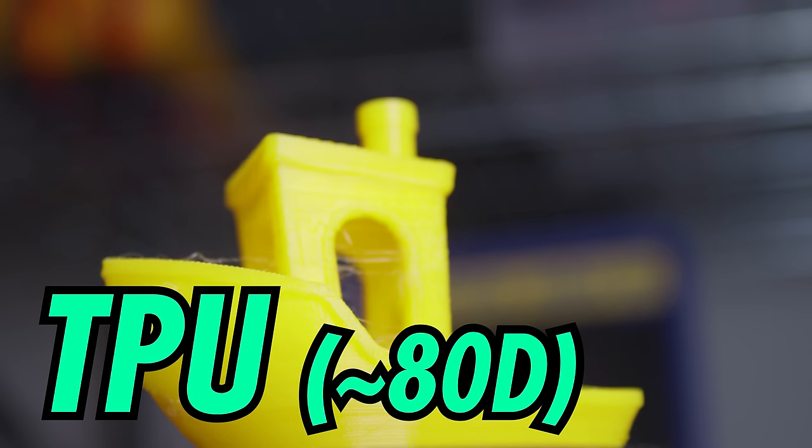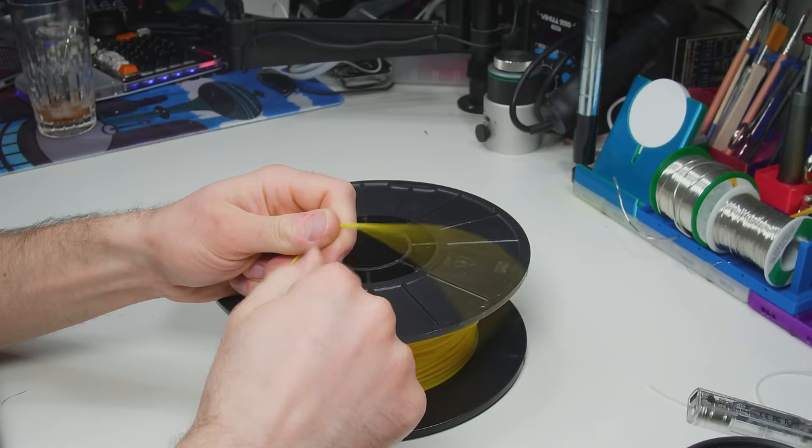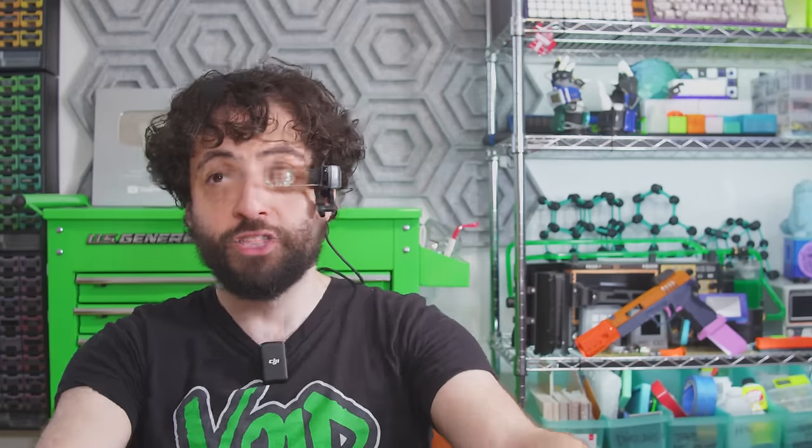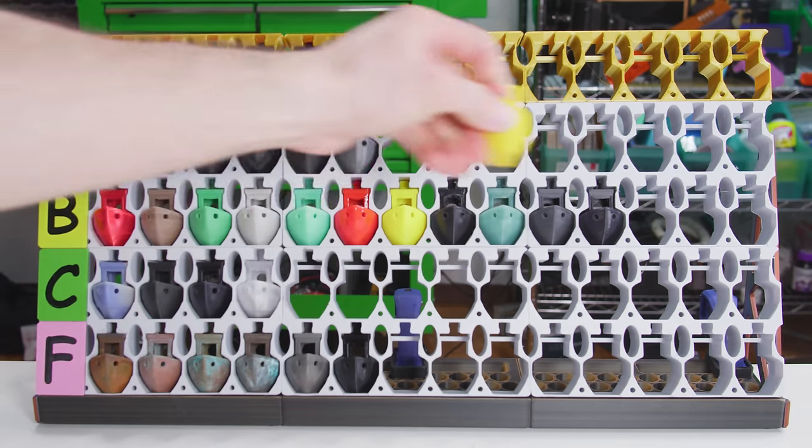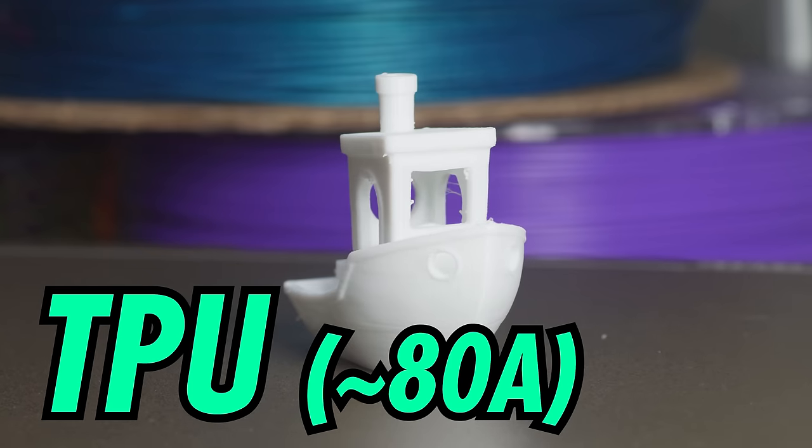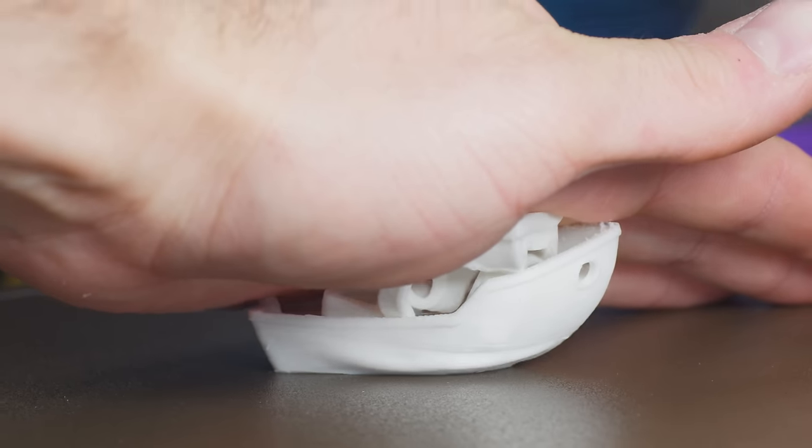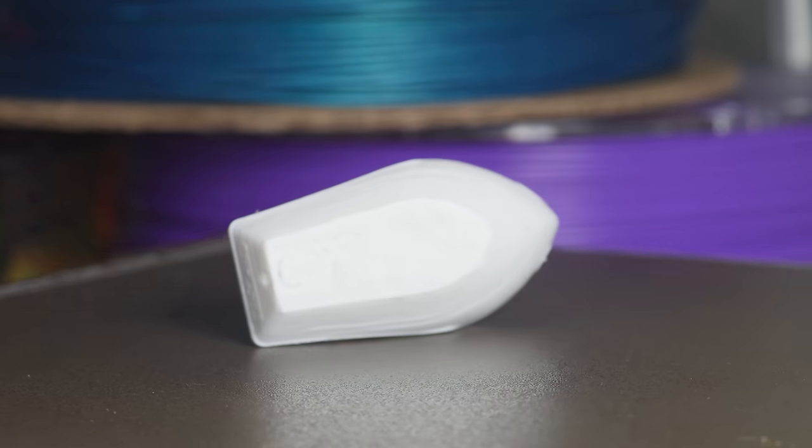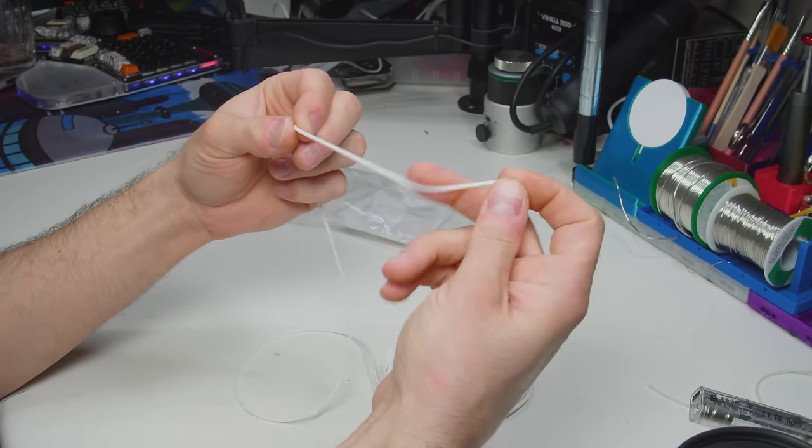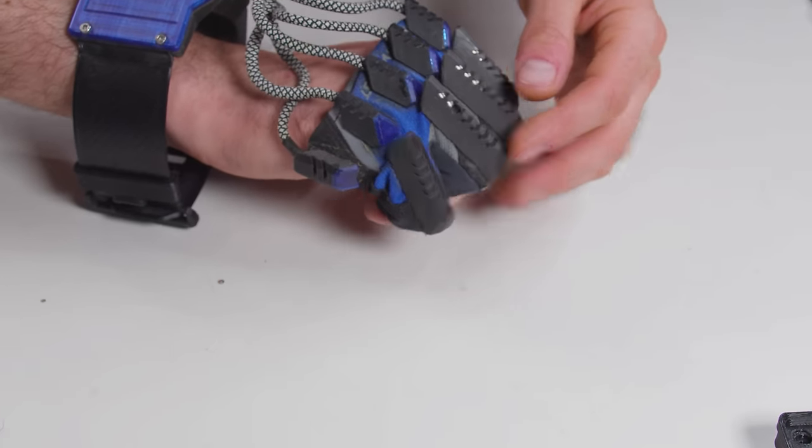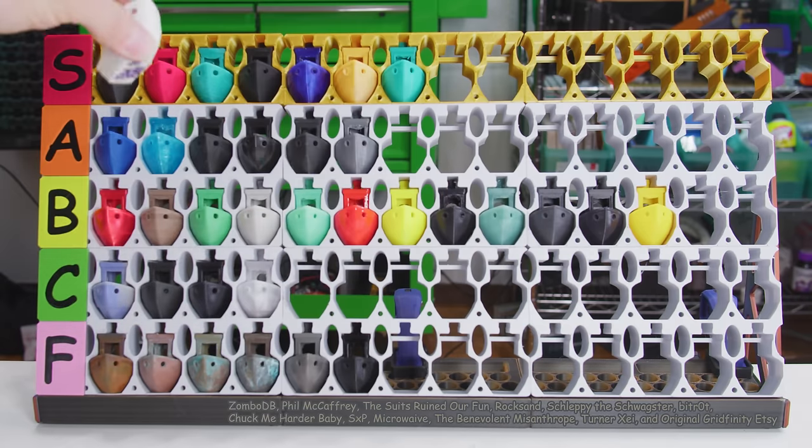80D durometer isn't soft per se, but it's also not stiff. It's as rigid as the sole of a running shoe, and a good balance for things like bumpers, hinges, and semi-legal Nerf melee weapons. It's also just as easy to print, as long as you don't try to make anything tall and thin. I'm gonna give semi-flexible TPU a B, since it's trickier to print, and it's too stiff for many projects, but too supple for others. 80A durometer TPU is about the softest you can get. This is unambiguously a floppy, flexible filament. This has a nasty habit of tying itself around your drive gear, so you have to maintain constant low speed and keep an eye on the printer. I don't really like this stuff. It seems like the obvious choice for wearables, but since TPU doesn't breathe, it instantly gets really sweaty and uncomfortable. I'm gonna put low durometer TPU in C-tier.